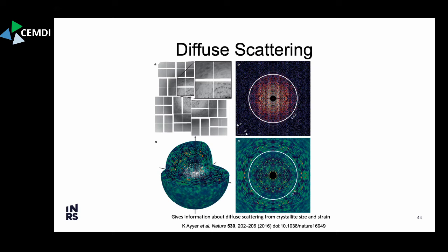And even still, you have information which you can't quite tell in a given diffraction pattern. So this is a single diffraction pattern from photosystem 1. This is another membrane protein. And so are these spots? I mean, this is, again, this diffuse intensity. But if you use the information about the orientation from the Bragg spots that you do have, and then you take these full detector images and you merge them into 3 dimensions, you can see that you have more structure and more information about the structure of the material extending up to a much higher resolution in reciprocal space.